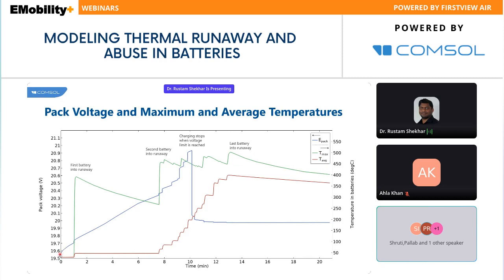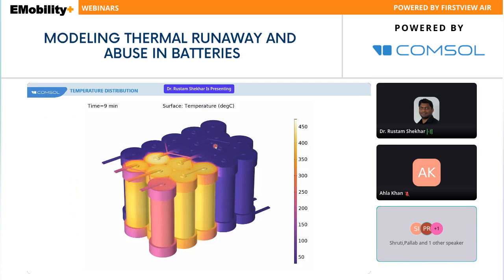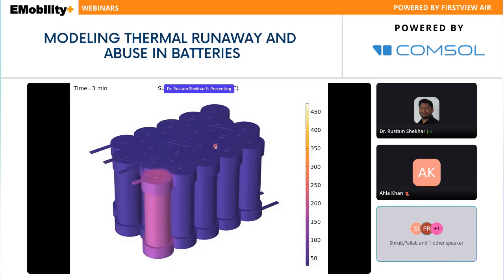T max, which you can see, is triggering very sharply, but T average is increasing very gradually, and it can reach up to the same temperature that T max is reaching. So T average and T max both can be handled, and then you can see the failure of this battery through the battery potential. Battery potential is increasing with the failure, and then ultimately it will drop down and die off. This way we can observe the pattern of the failure of our cell. That can be seen in this kind of animation.